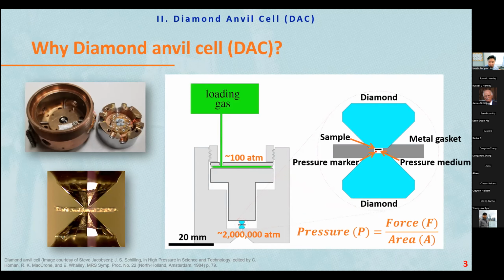The important part is that when you apply only 100 atmosphere on the cell, you can generate 2 million atmosphere on the tip of the diamond because the tip is very small. So according to this equation, you will get very high pressure. And not only that, the diamond also has transparency. So it's very good for spectroscopy measurement.